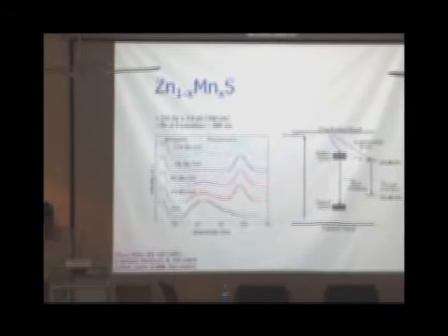Okay. Now, since I talked about gallium manganese arsenide, the other doped system which we have been looking at is zinc manganese sulfide. I will not go into much detail over here, but zinc sulfide has surface states, defect states. Well, most of the defects in a particle are on the surface, since most of it is the surface and all of them are dangling bonds. So, defect state emissions and manganese d-d emissions. Manganese d-d emission is typically around the yellow region. You get some blue defect state emissions. Combine them, get some white light emitting particles.